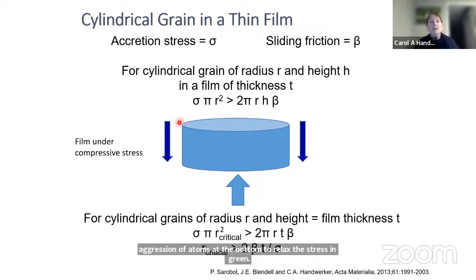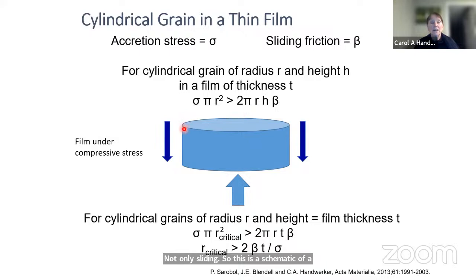So this is a schematic of a cylindrical grain in a film. Imagine most of the grains in the film look sort of like this, but this is just a schematic of a cylindrical one. It's got a radius R, a height H, and the film thickness T. And if all of these are the same, there's a grain boundary sliding stress, because remember, this grain is being constrained by being in a compressively stressed film, so it actually takes a force to push the grain out against the sliding stress.